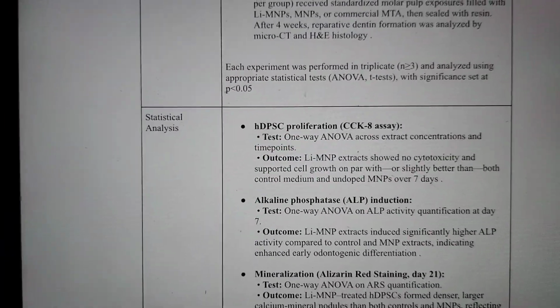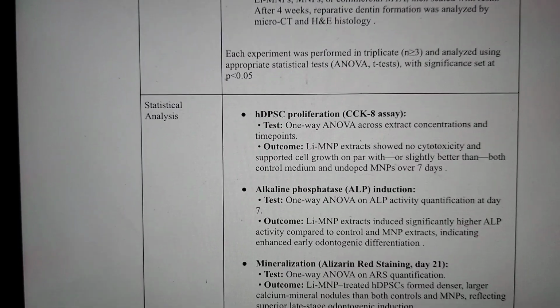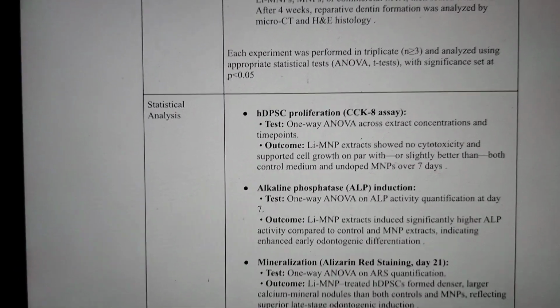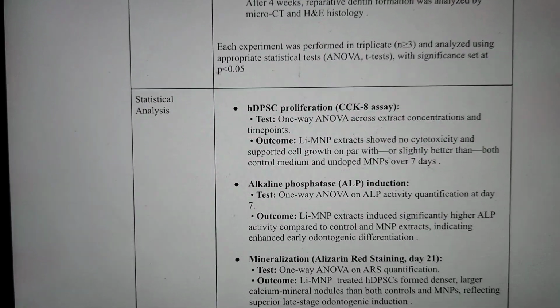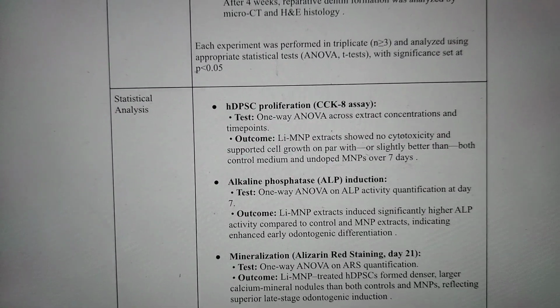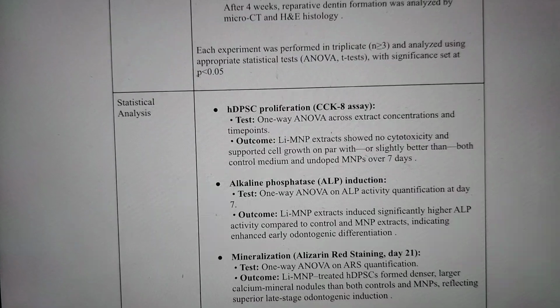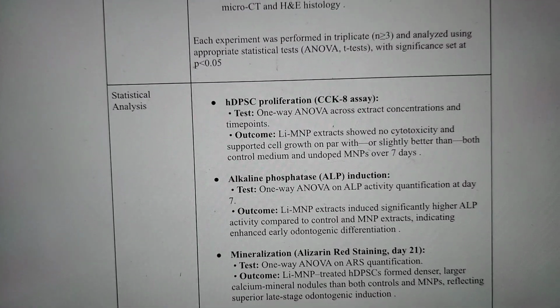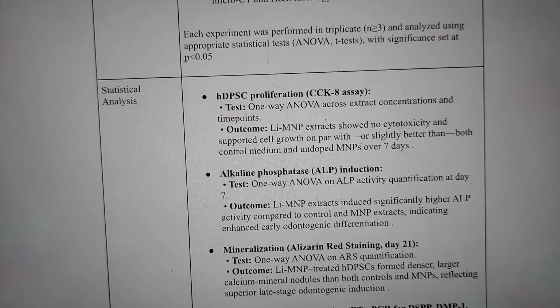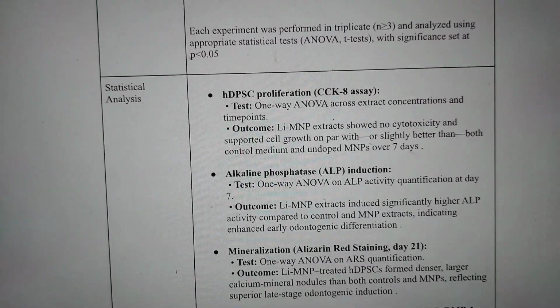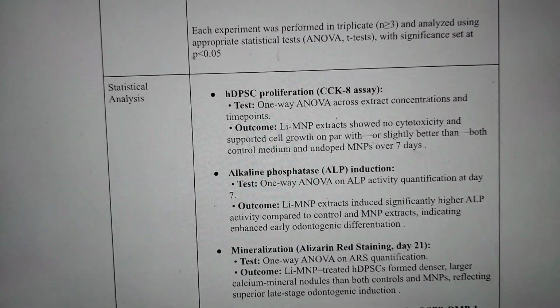Statistical analysis of HDPSC proliferation by a CCK8 assay used one-way ANOVA. Outcomes showed the extract showed no cytotoxicity and supported cell growth on par with or slightly better than both control medium and undoped nanoparticles over 7 days.